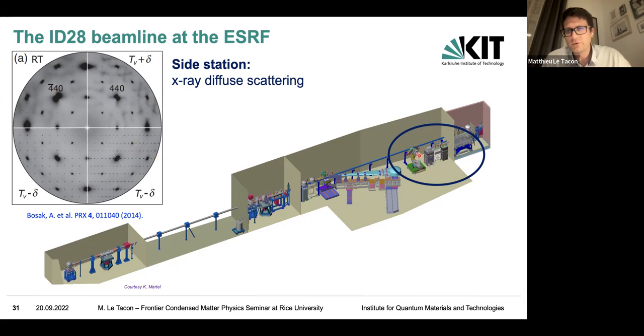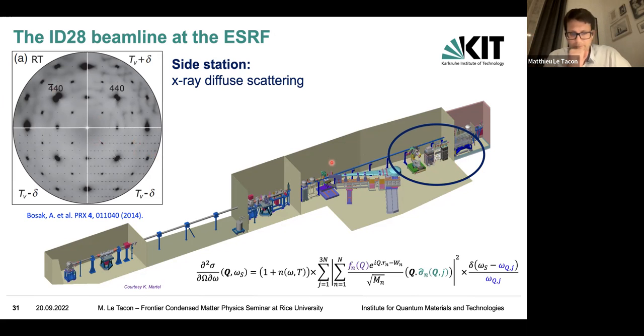In other words, what you do here is an inelastic X-ray scattering experiment, but you integrate over the scattered energy. So that's the inelastic X-ray scattering cross-section. There is a Bose factor, there is a structure factor, basically telling you that the more electrons you have, the better you scatter. There is a selection rule, telling you that you have to align your momentum transfer with the polarization of the phonon if you want to see it. And there is a delta function for the energy selection.